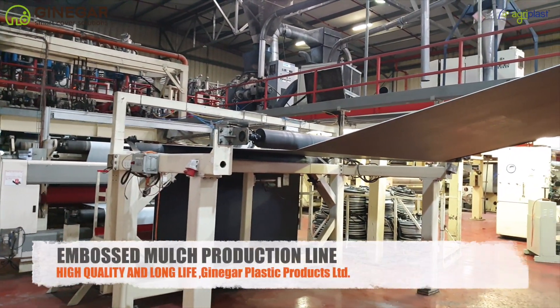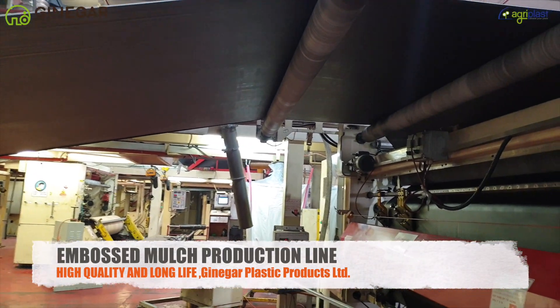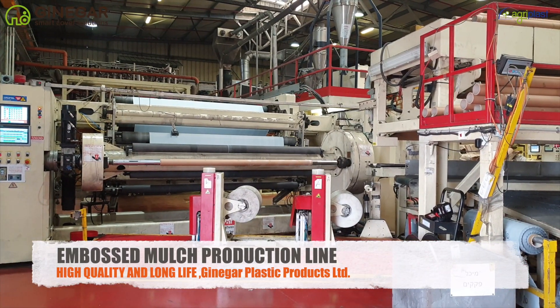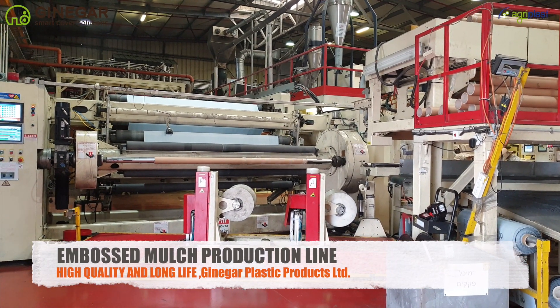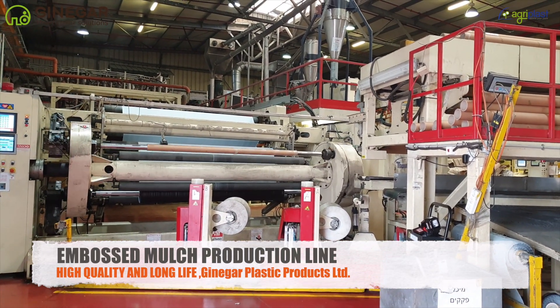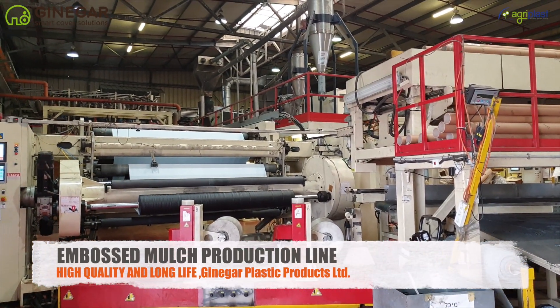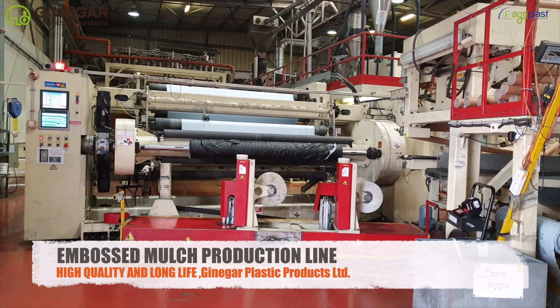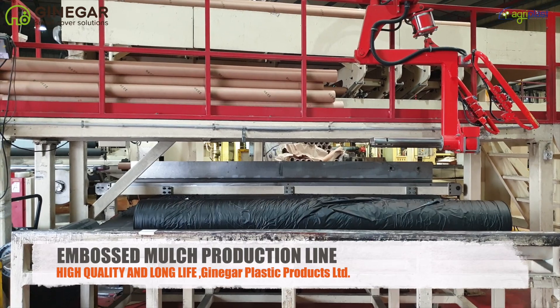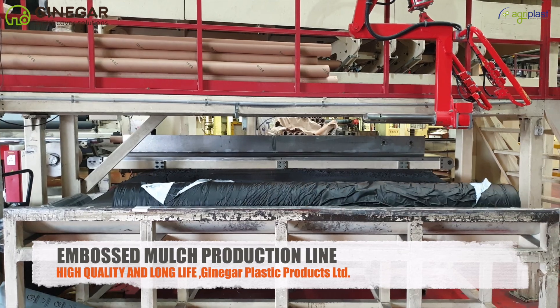Ginegar's mulch films are advanced multi-layer mulch films manufactured using two methods: multi-layer blown film co-extrusion and cast flat die extrusion. Offering UV protection, these films are available either embossed, cast, or smooth blown, and in a wide range of thicknesses and widths according to specific grower needs, specifications and crops. The cast production method involves embossing while the material is hot, thereby changing the surface of the sheeting and endowing it with greater flexibility, softness and strength.